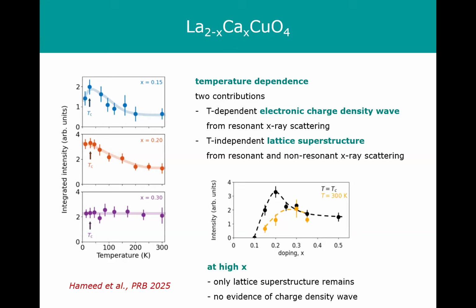Okay, so at moderate doping levels, you see some intensity remaining at high temperatures, and then a second component coming in at low temperatures. But at high doping levels, everything is temperature independent, which means only the lattice structure remains. There's no evidence of the previously reported charge density wave formation. So we only have a lattice superstructure. But then at low doping levels, we have both.